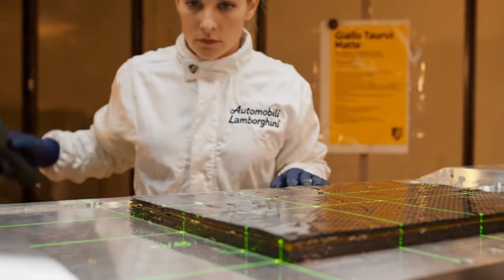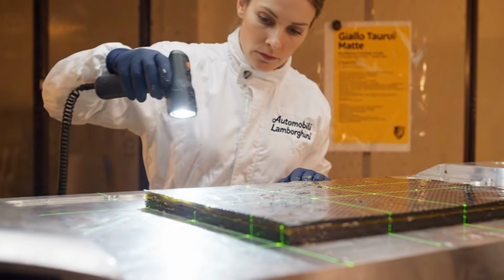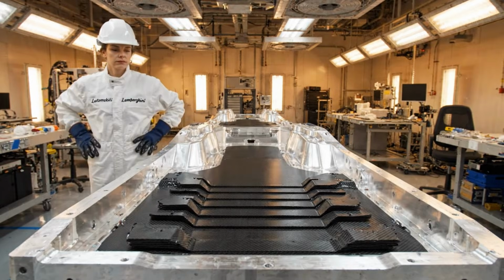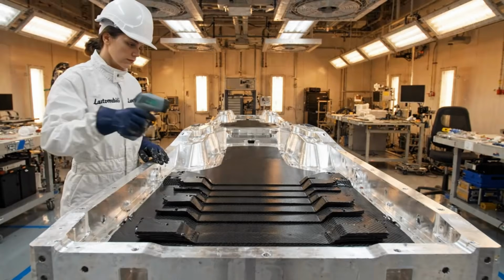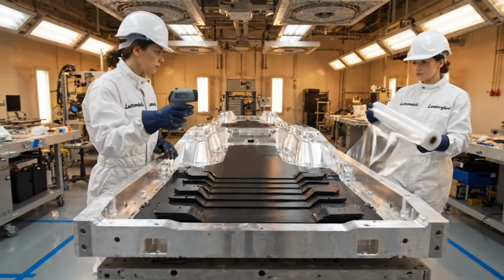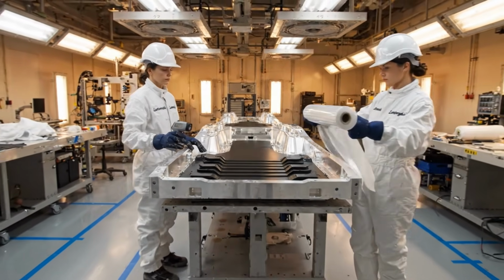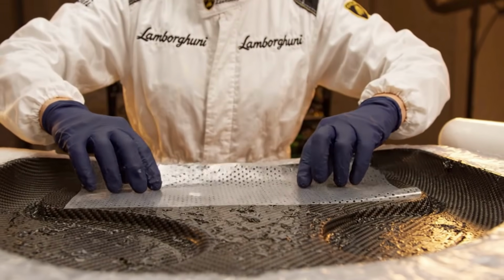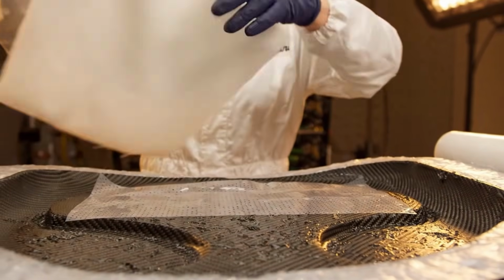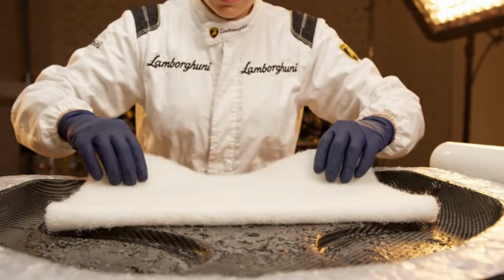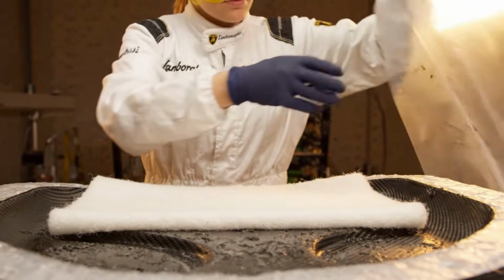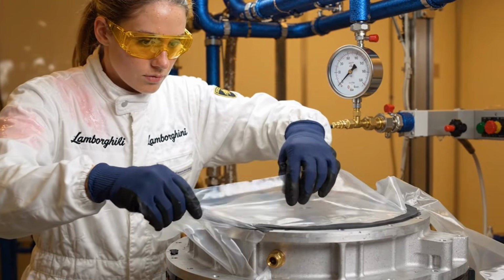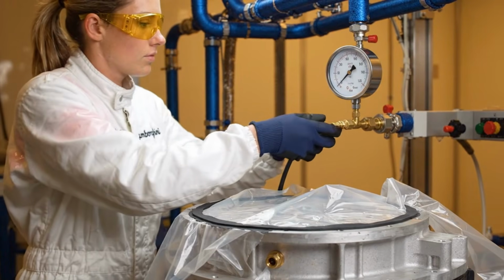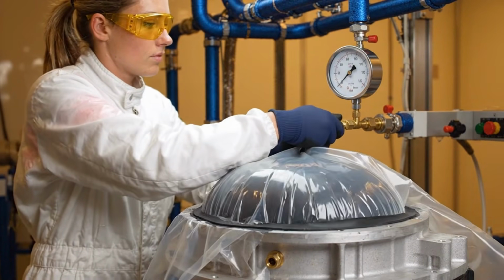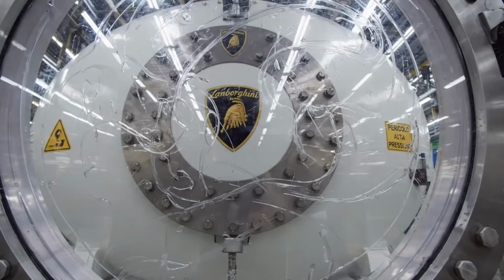By the sixth ply, the laminate has reached 1.5 millimeters in thickness. With 12 plies of carbon fiber laid at precisely specified orientations, the floor section of the monocoque now contains the layers. The release film and breather fabric are layered over the uncured laminate, ensuring the vacuum pressure reaches every point on the mold surface. The vacuum bag is sealed to the mold flange with a continuous bead of butyl tape, and the air is evacuated to create a pressure differential that will compact the laminate during the autoclave cycle.